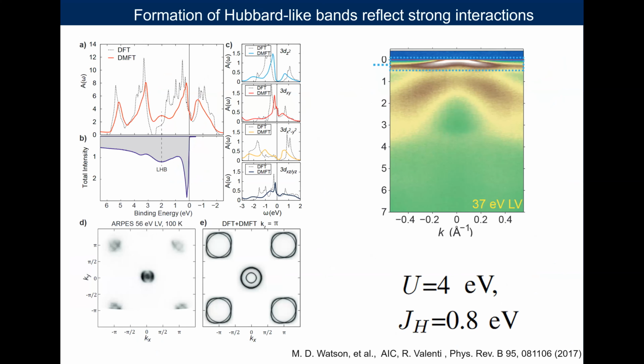Iron selenium also shows some signature of the lower Hubbard band, which is a signature that it's a strongly correlated system, and these are DFT calculations performed by Roser Valentí's group. And even if this type of interaction is taken into account, these are the calculations here, and these are the experiments on the left side, the Fermi surfaces are still not fully captured at very low energies.